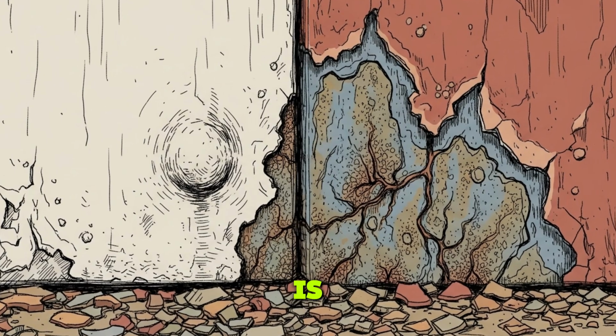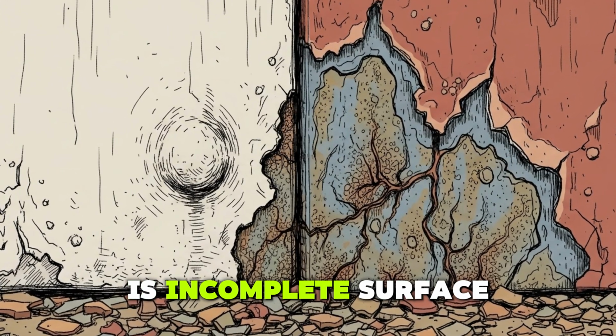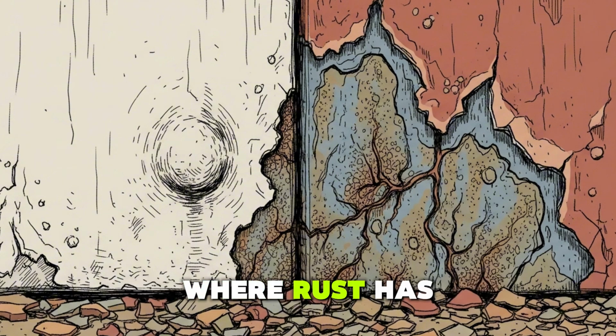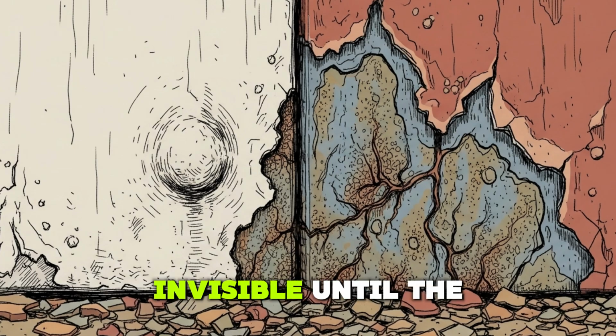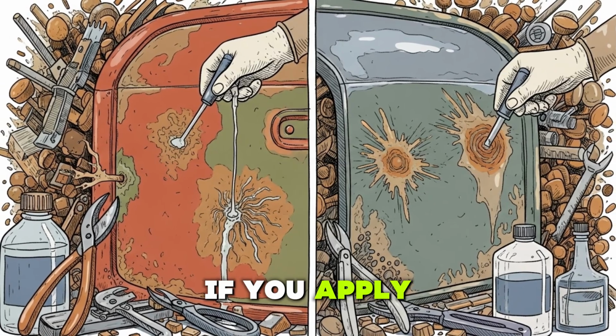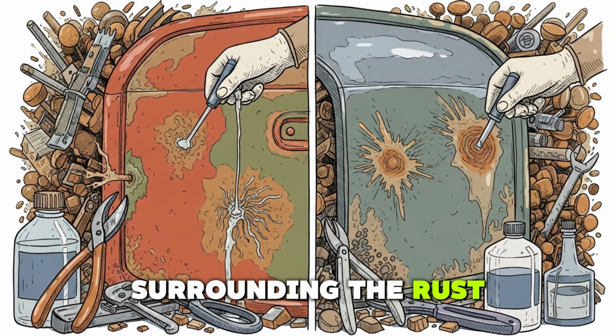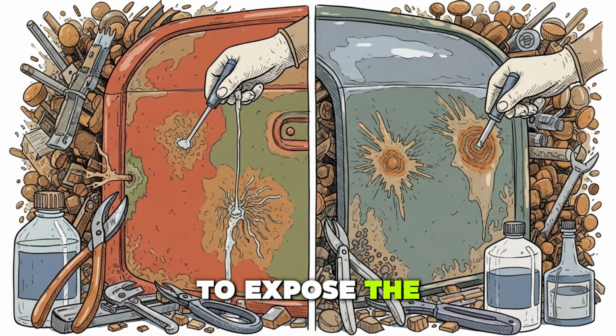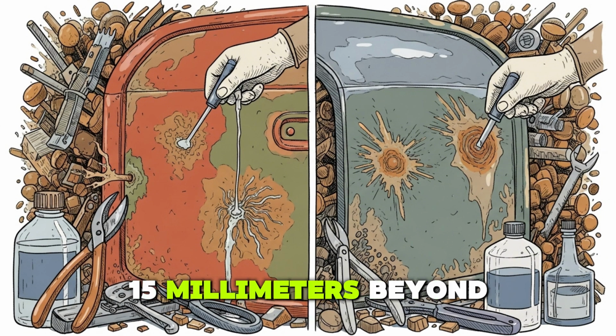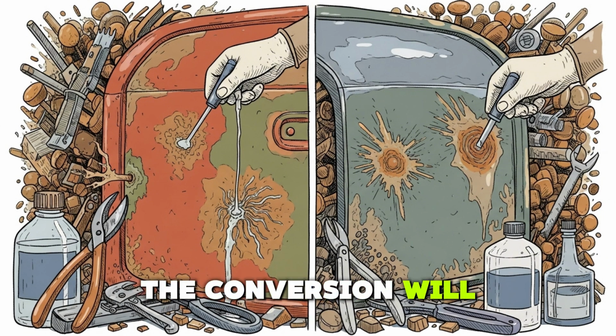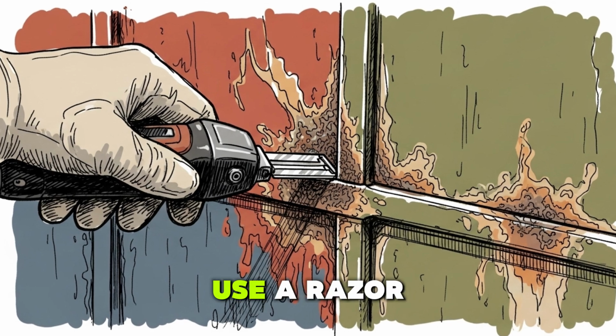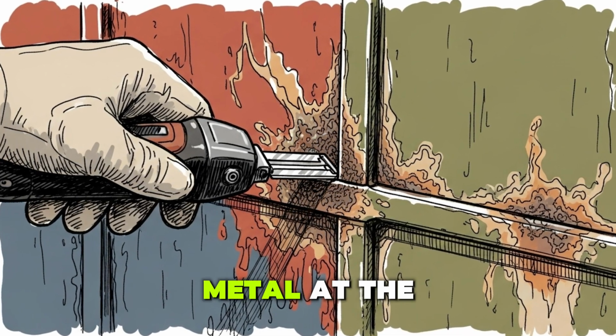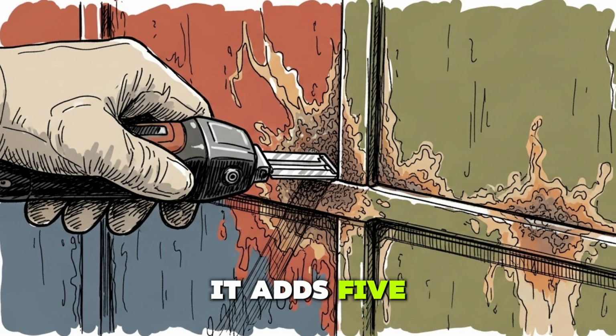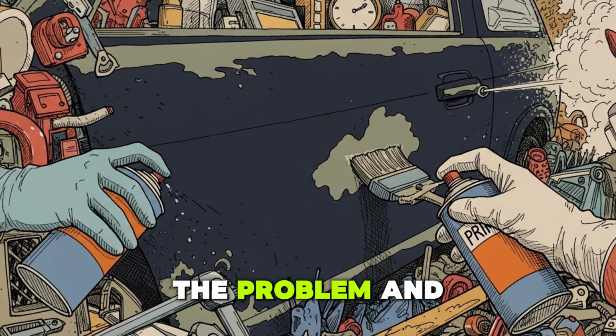Removal and replacement is. The second category of critical failure is incomplete surface preparation on painted panels, where rust has begun migrating beneath an intact paint layer. This is called undercutting, and it is invisible until the paint begins bubbling. If you apply phosphoric acid over the painted surface surrounding the rust, without first cutting back the paint to expose the full rust boundary, typically 10 to 15 mm beyond the visible rust edge, the conversion will treat only the exposed center while the migrating rust beneath the paint continues uninterrupted. Use a razor blade or oscillating tool to cut back paint to clean metal at the perimeter before you begin. It adds 5 minutes to the job and is the difference between solving the problem and framing it.